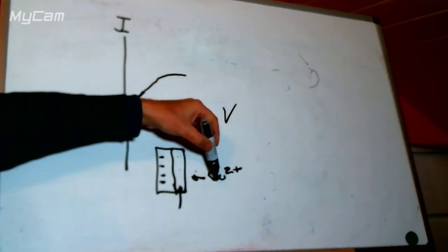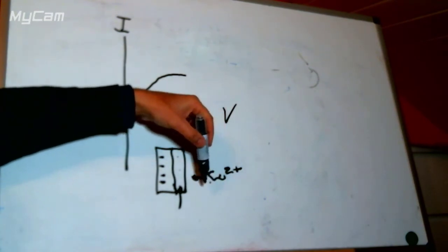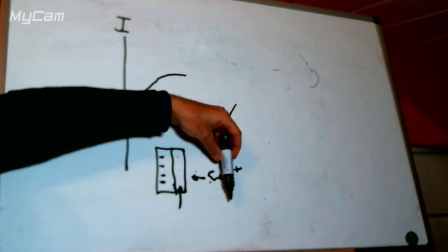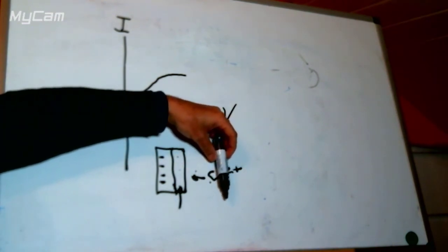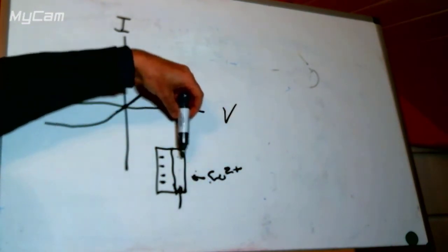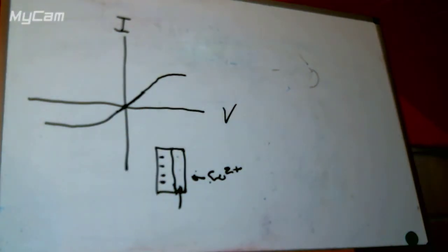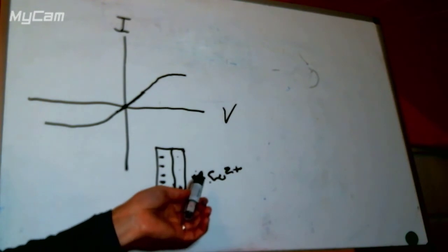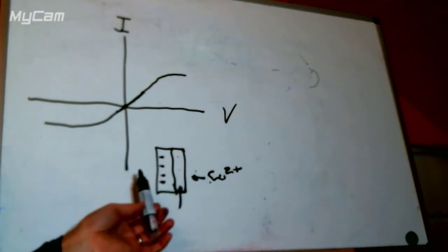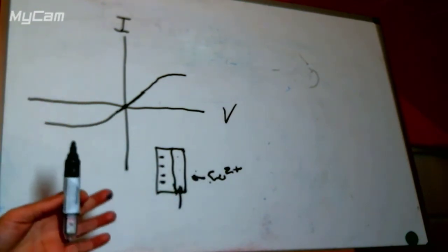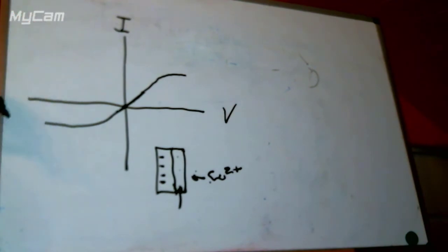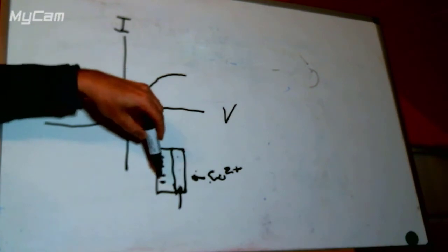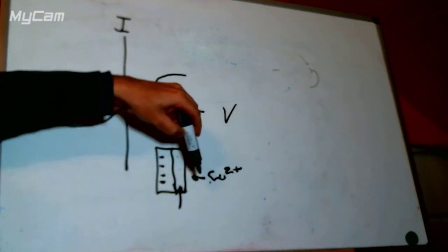And so the copper ion out here doesn't see the electrode as being negative. If we push negative ions out into here, then the area close to the electrode will look like it's not charged there. If we're inside that region, we're not actually being pushed with the voltage further in. What that means is that it's very hard to increase the current beyond whatever the concentration can support.